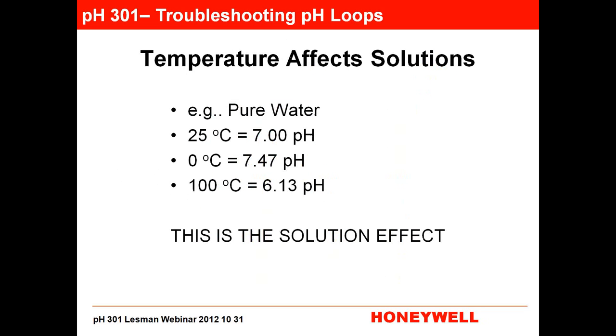This is my favorite example because everybody knows water, and we understand water, and we can think about water all together and get a good picture of what's going on. So if you have water that is 100% pure, doesn't have any contaminants whatsoever, and it's in a sealed environment, because the minute you open it to the atmosphere, it will start contaminating. Certainly if it's around a salesperson like me, all that hot air coming out, all that CO2, that's going to contaminate your water and cause the pH to go down and the conductivity to go up because it dissolves in the water. So we want to keep this completely sealed in our example.